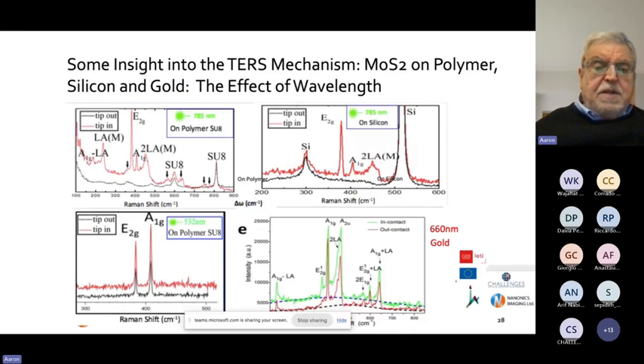Here is different materials, but also different wavelengths. This is a wavelength at 785 nanometers of the same material on the same substrate, and what it looks like at 532, okay? And this is an example of silicon with 785, okay? And I'm sorry, this is an example, all of this is a molybdenum sulfide, excuse me. This is on silicon and this is on gold. So depending on the wavelength and depending on the material for that matter, on which the sample is sitting, you see different enhancement, okay?